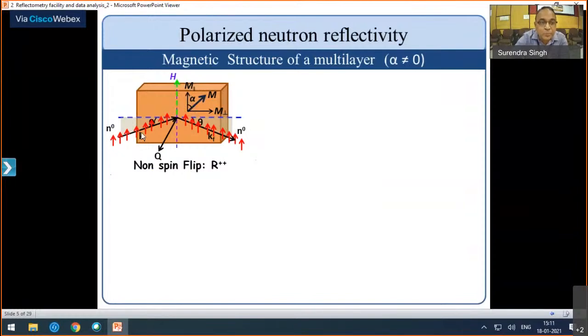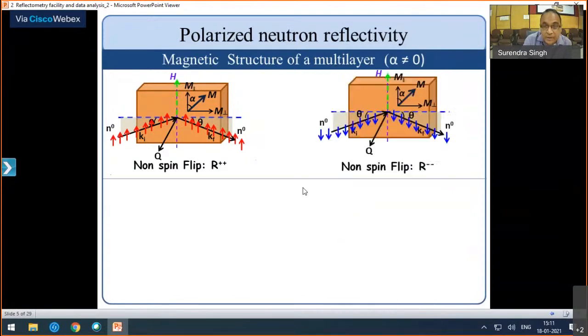Here we have a parallel component - it won't precess any spin, the neutron spin, but we have the perpendicular component, m perpendicular, which is perpendicular to the neutron spin. So these spins get precessed, so they can change their spin directions. Okay, so here the case will be different. So let us see, suppose we have a spin up neutron coming in, then if we have spin up after reflection, this is one possible thing if we have both m parallel and perpendicular components. But if there is precession of spin after interaction, because we have this perpendicular component, what will happen?